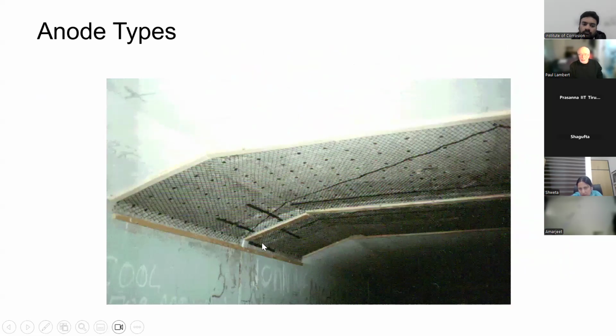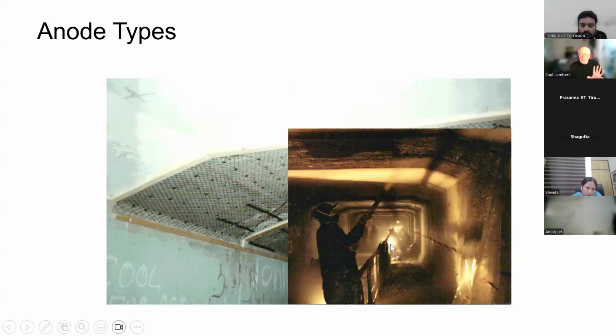In terms of applying it, this is the underneath of a tunnel deck. You can see the mesh is the coated titanium mesh. The little black dots are plastic fixings that hold it in place. The dark lines you can see are ribbons that are being used to distribute the current and also boost it in certain areas. That won't work on its own. It needs to be embedded in mortar, and what they tend to do there is use sprayed concrete. So it's a dry sprayed concrete. It goes over that. It protects the mesh. It acts as the electrolyte. It provides the environment in which you continue to operate. And that's proved to be a very, very effective system in infrastructure repair.